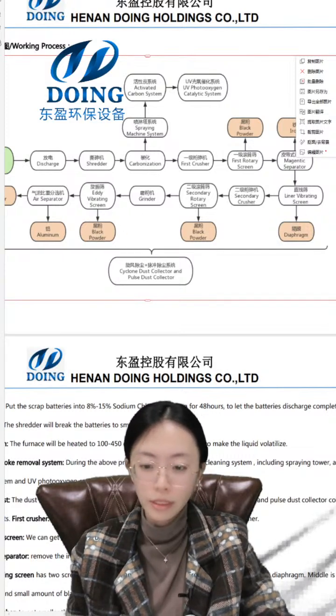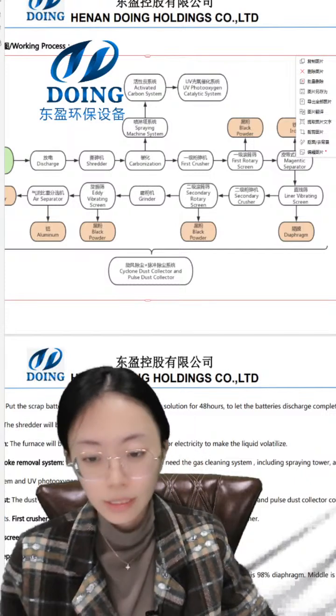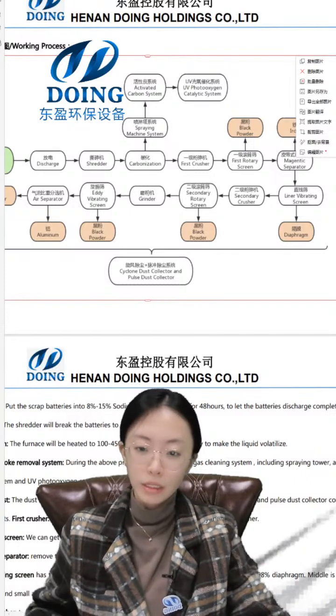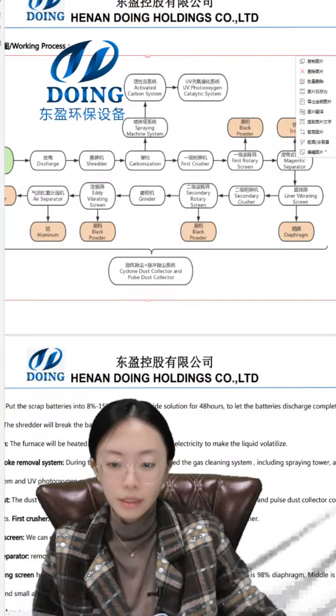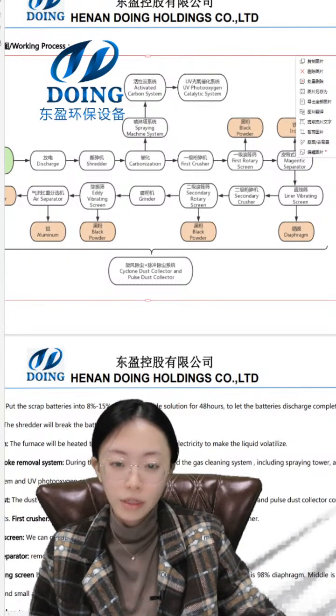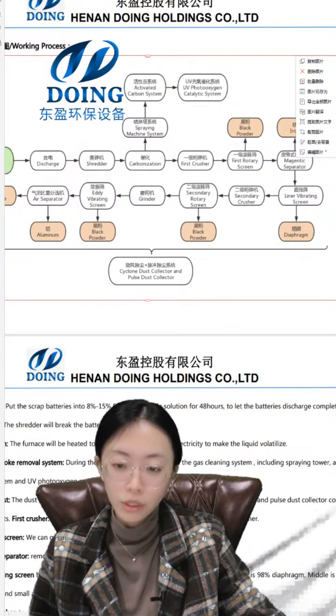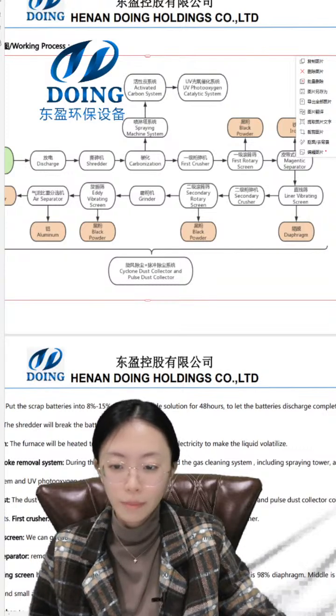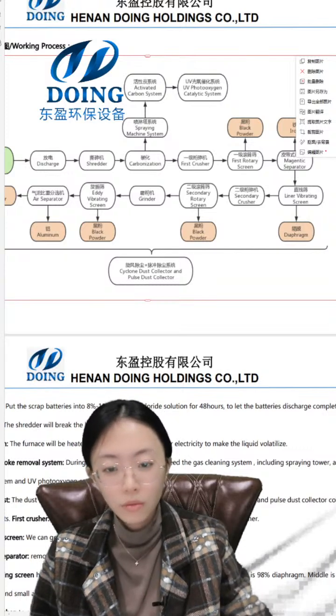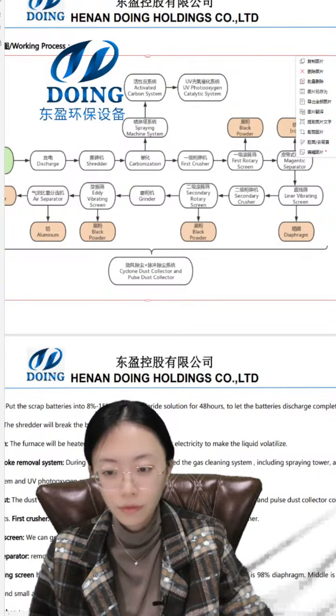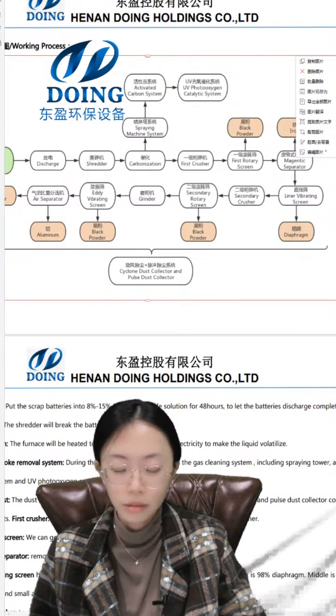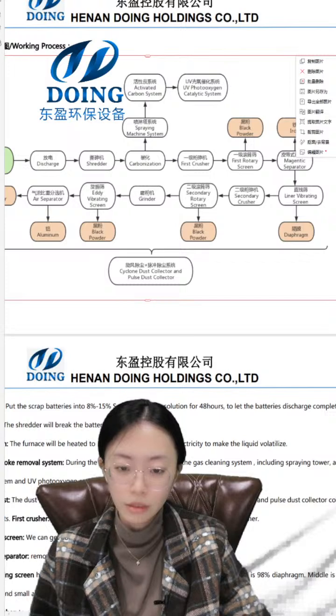Then the vibrating screen. The grinder is connected with the vibrating screen. The rotary vibrating sieve is equipped with a 50 mesh screen in the upper layer and a 120 mesh in the lower layer. So a small amount of the black powder comes out of the lower layer of the rotary sieve, and the middle layer of the material, the copper aluminium mixture, goes into the next layer for the separation.